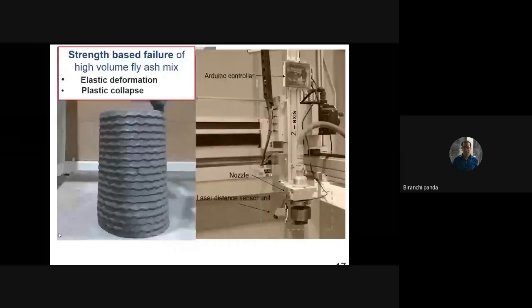And to measure this deformation, we have modified our printer. We attached a laser sensor to the extruder, so that during printing, this sensor measures the deformation of the layer. This information is really helpful because we developed a feedback control system. When the material is going to deform, the laser gives me real-time data, and with that real-time data, I can optimize the material design and the printing parameters in such a way that I can reduce the deformation.